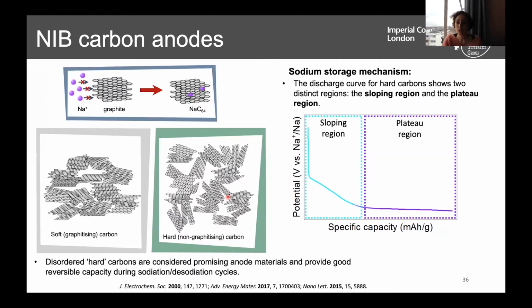So the second approach that we were thinking with these fibers was as carbon anodes. As I mentioned before, graphitic structures are not able to intercalate sodium, and that's why we have to use hard carbons that are produced from different sources. And basically, in the sodium ion storage mechanism, we can see two different regions: the sloping region and the plateau region. And each of these parts of the ion storage within the carbon is related to different features of the texture, the porosity, the defects, the interlayer spacing of the carbon.